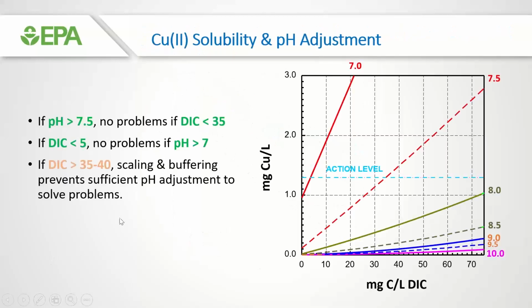So from a practical standpoint, another way to look at this, we plotted up here different pHs versus milligrams of copper per liter versus the DIC. And here's the action level, which, by the way, is a health-based action level. It's an MCLG of 1.3. And the point here is that if you're at a pH of greater than 7.5 and your DIC is less than 35 from this diagram, you're not going to have high copper levels associated with that new plumbing, the worst case situation. Same thing goes for the conditions where you have a DIC of less than 5 and a pH greater than 7. But if you're in that situation where you're at, let's say, pH 7.5, but your DIC is 50 or 60 or 70, and that's something we see a lot in the Midwest, these kinds of waters, you're going to have a bit of a problem. Copper levels could be high in the newer plumbing, in particular.